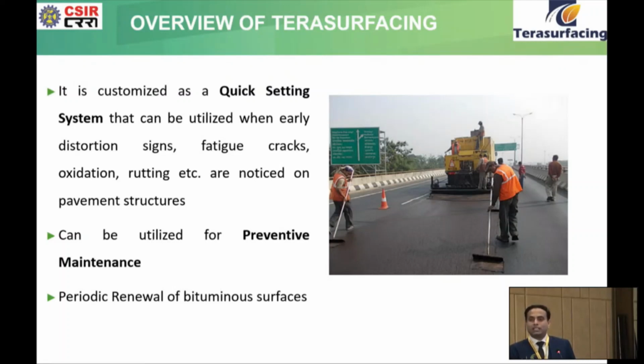Recently we accomplished this work in Surat, Hazira, where we utilized the processed steel slag aggregate fines of ArcelorMittal Nippon Steel for the construction of this road. One of the important aspects is that it's a quick rehabilitation method, with in situ preparation and in situ laying mechanism. You can open the road for traffic movement within 2 hours itself, since there is no heating of aggregate and bitumen involved. Besides that, the cost of maintenance is also very less. The entire cost of the treatment will vary between 120 to 140 rupees per square meter, which is substantially economical in comparison to the conventional treatment.